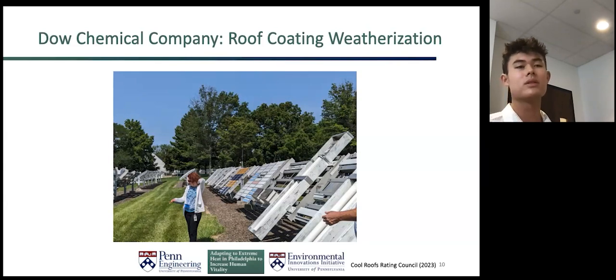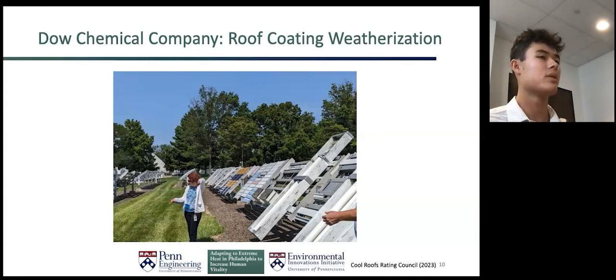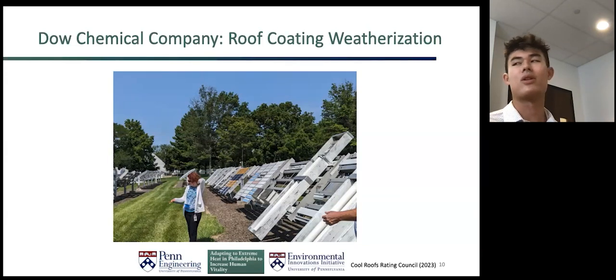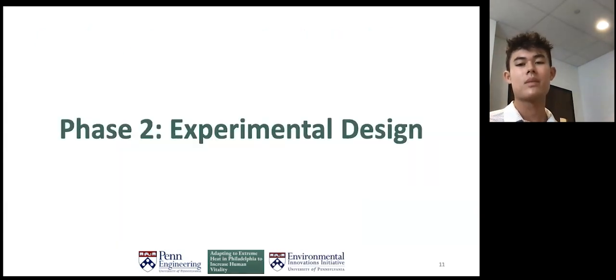And this is actually a big problem with a lot of existing coatings. The Cool Roofs Rating Council studied thousands of different coatings and measured their solar reflectance index, which is a composite value of a material's reflectance and emittance. And they found that after just 3 years, a lot of coatings' SRI decreased by over 50% and more than 100 decreased by over 25%. So it's really important that our highest performing materials are able to maintain their SRI for many years so we can have cost-effective solutions that don't need to be replaced year after year.